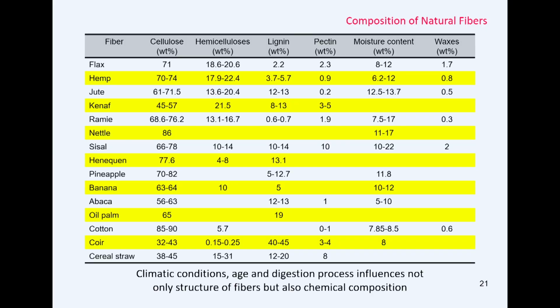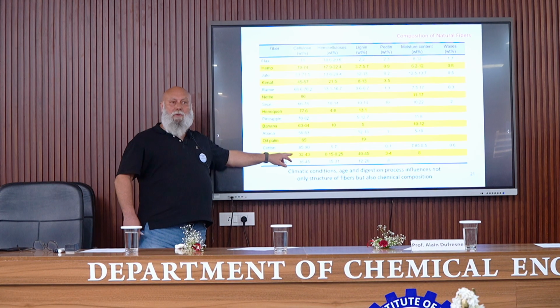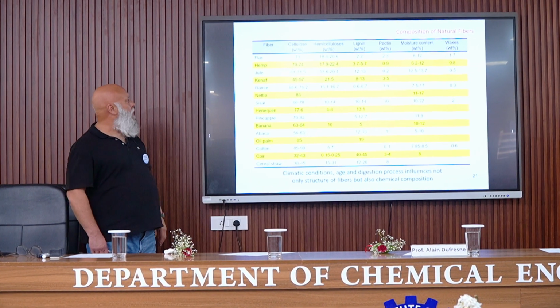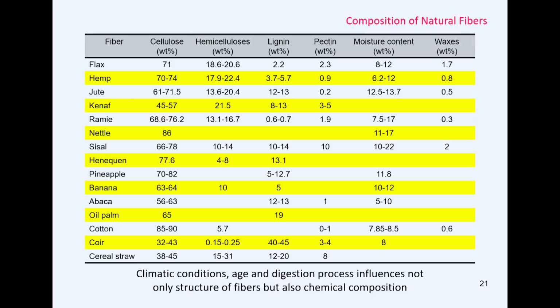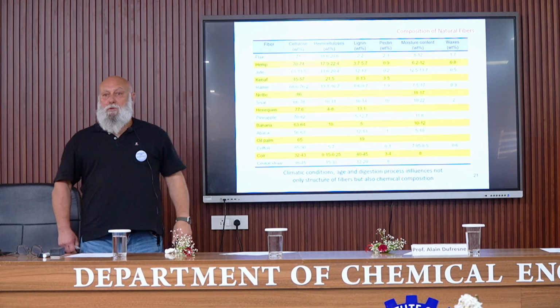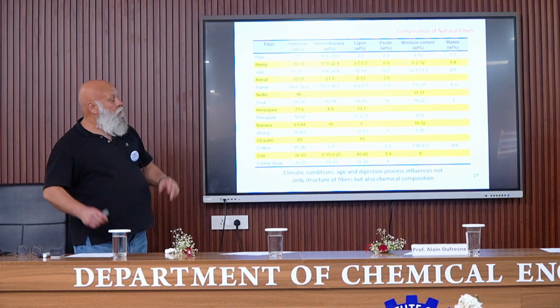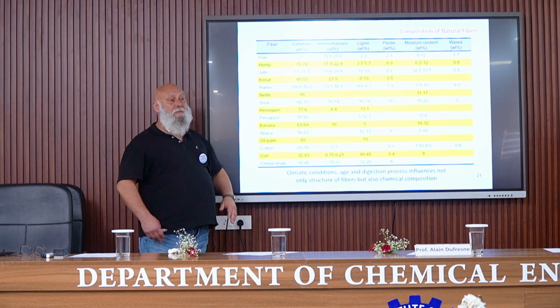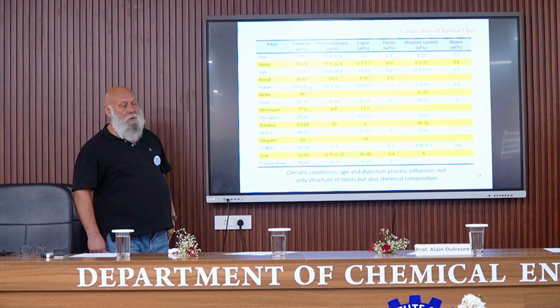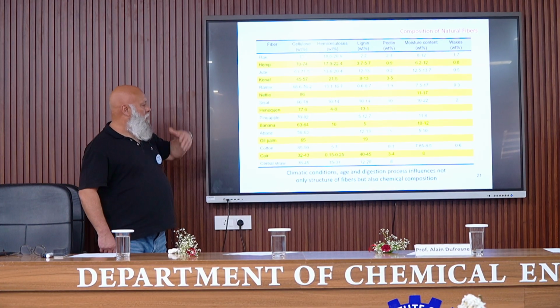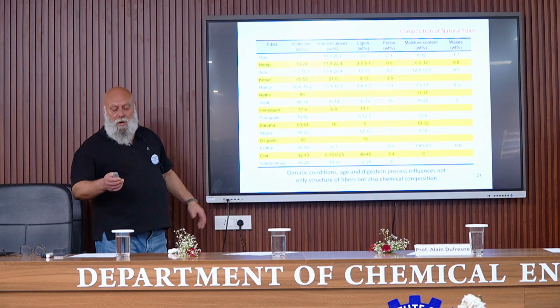So depending on the source of natural fibers, the chemical composition can vary. You have here some examples of natural fibers with the cellulose content, hemicellulose content, lignin, and some other constituents. We can see, for example, for coir, the cellulose content is very low, but the lignin content is high. On the opposite, in the case of flax or hemp, the cellulose content is important. And we'll see that this chemical composition, of course, impacts the structural properties of the natural fibers. I also previously mentioned that this composition can vary depending on the climatic conditions, the age of the plant, the digestion process, and some other elements, so it's a natural product.